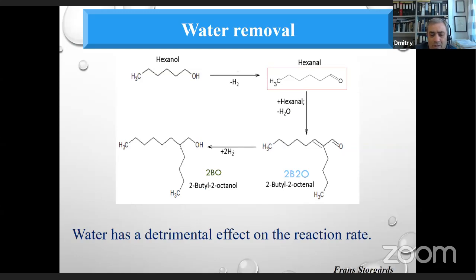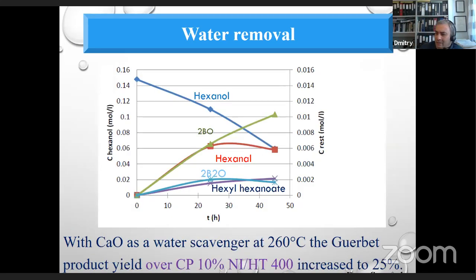Actually, water turned out to have a detrimental effect on the reaction rate, and then we started to think, is it possible somehow to improve the reaction rate and even the thermodynamics by removing water? So the best results that we have obtained so far, and at least that's what we published, were with co-precipitated nickel and hydrotalcites using calcium oxide as a water scavenger. We had to increase the temperature a little bit, so the Guerbet product yield increased to 25%. That is the best result that we were able to obtain so far.